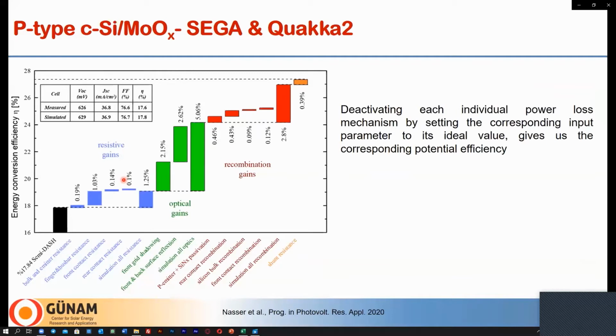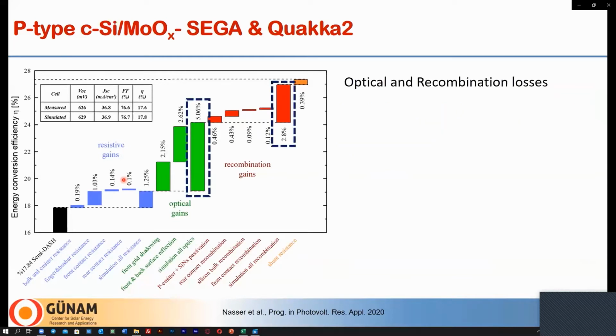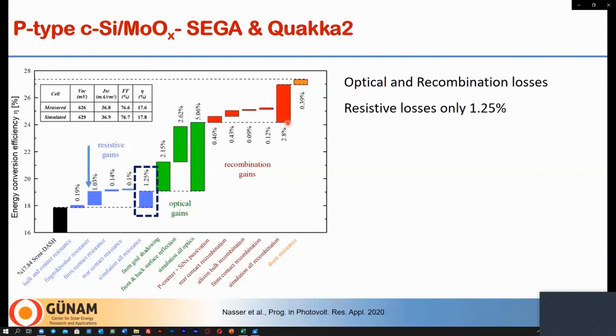So this loss analysis shows that our solar cell has two dominating loss mechanisms. The first one is optical losses of almost 5%. The second one is recombination losses with 2.8%. On the other hand, resistive losses show only 1.25%. Some of these losses can, of course, be avoided or reduced.